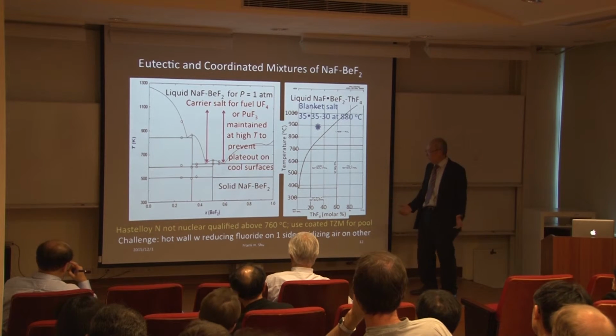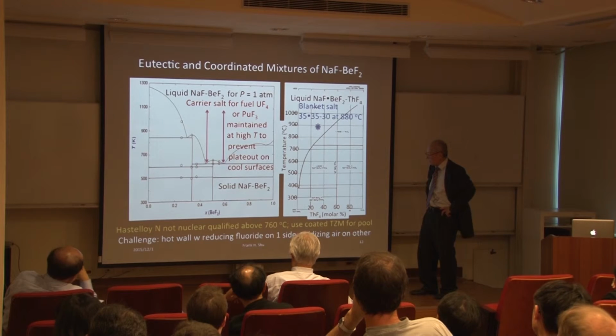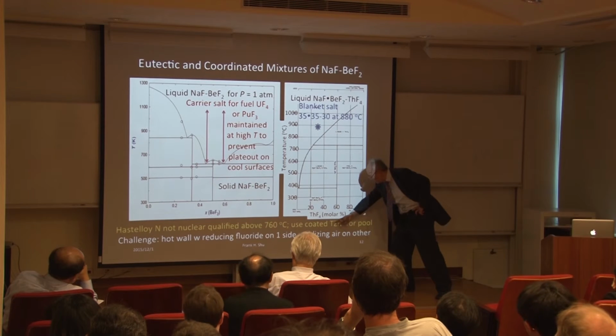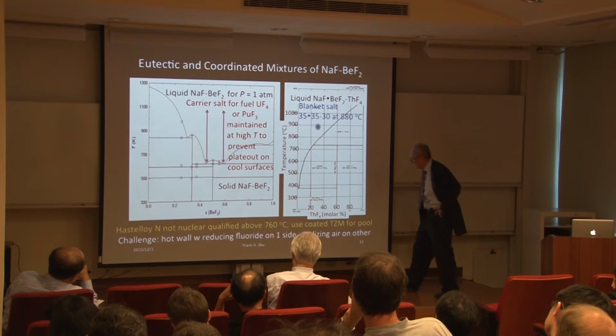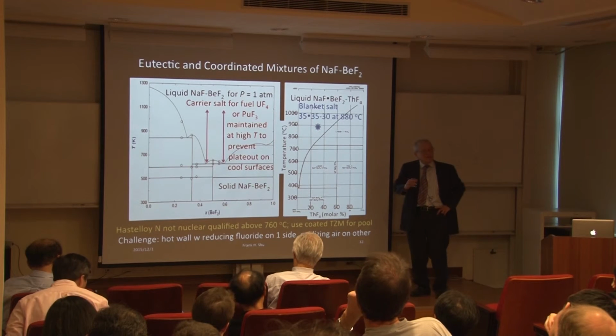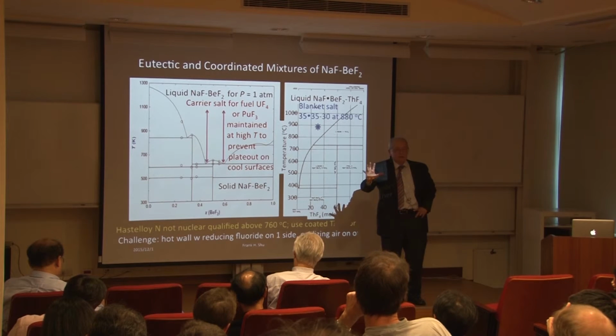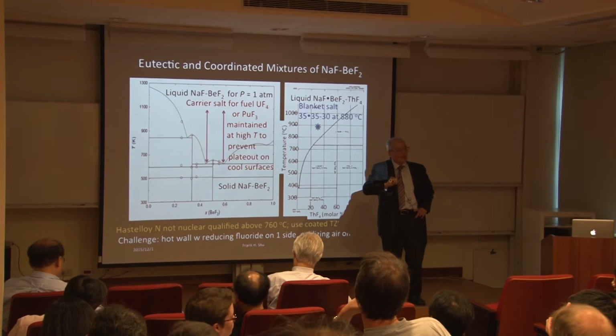So what should we use? Well, I think I already showed it. We are proposing using an alloy called TZM. M stands for molybdenum, T stands for titanium, Z stands for zirconium. Why molybdenum? Molybdenum is the least metal-like of metals. It's almost a non-metal. And for that reason, it's not easily corroded. Okay? But unfortunately, it's easily oxidized by oxygen. So you better protect it.